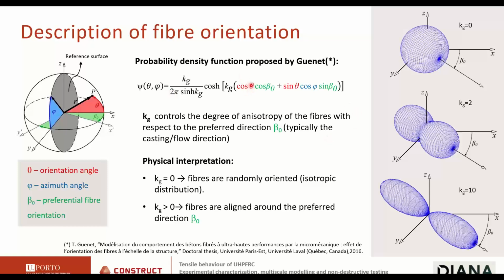You see here the two angles that we need to describe the fiber orientation, theta and the azimuth angle. And it's also useful to have here a direction of preferential fiber orientation. So the direction along which you will find your probability density function will have the highest value. The only parameter that governs this function is this Kg factor, which controls basically the degree of anisotropy of the fibers with respect to the preferential direction, typically the casting or the flow direction of the material.